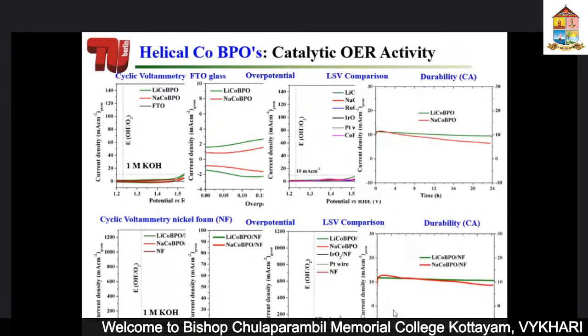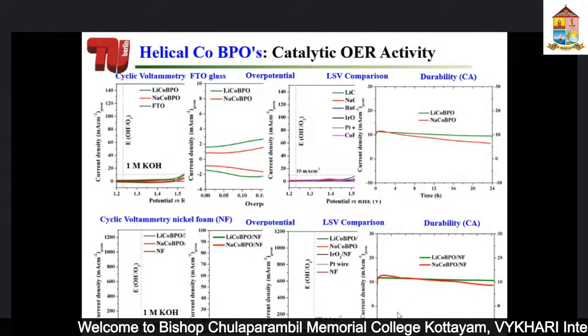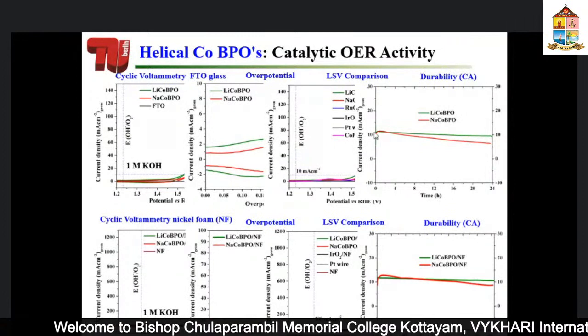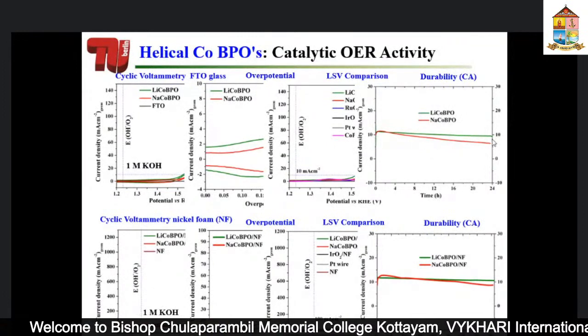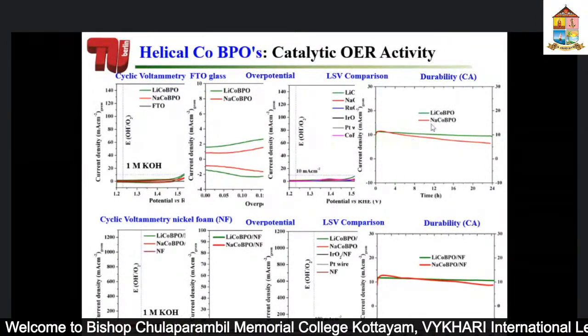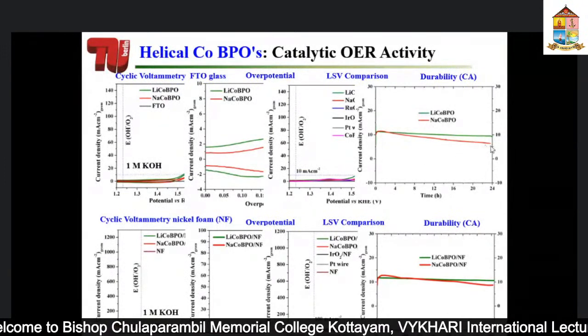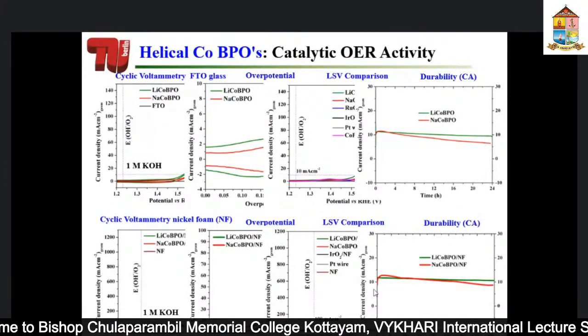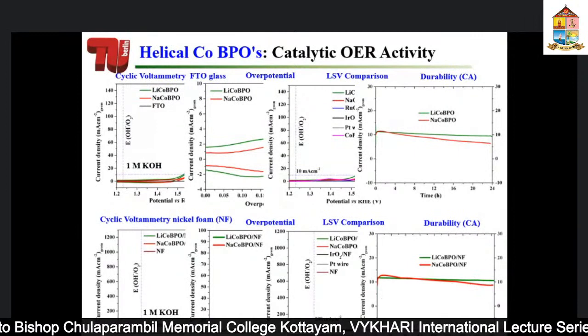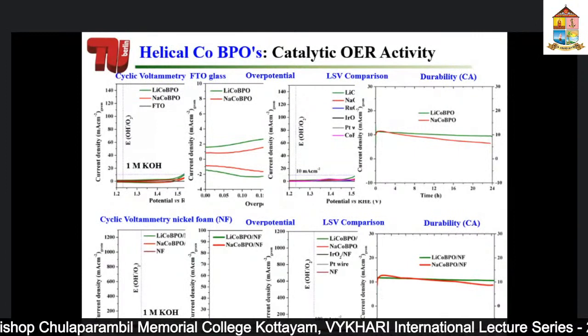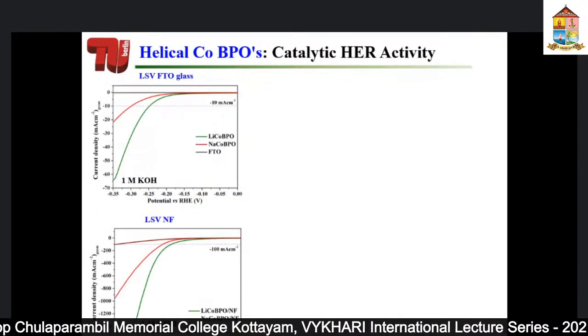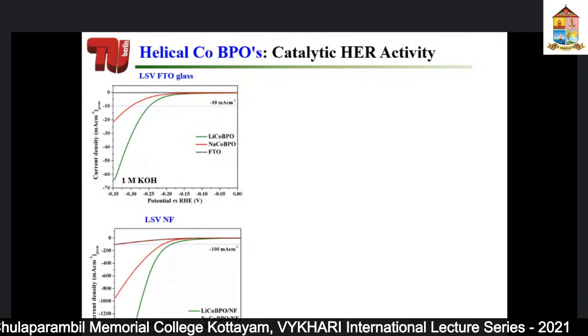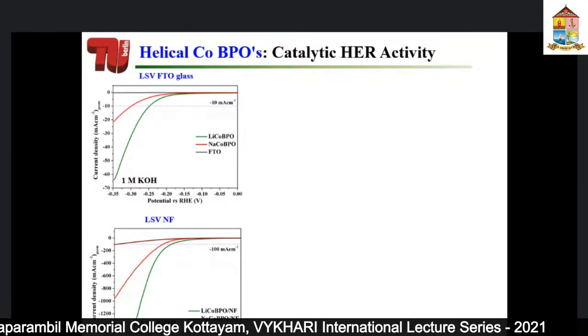As I said, it's also important to have better stability. What you would see here is that they are stable for 24 hours. Some, for example in the case of sodium, are decreasing a bit, but you still see a very nice trend for all these catalysts as they are very much stable. So this is one half of the reaction where we produce oxygen. The other half is to produce hydrogen.